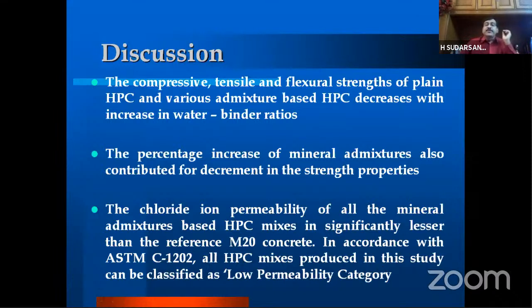This has been used to derive the water binder ratio relationship with strength properties and the durability properties. Chloride ion permeability has been measured with a chloride ion permeability apparatus as per ASTM C1202.